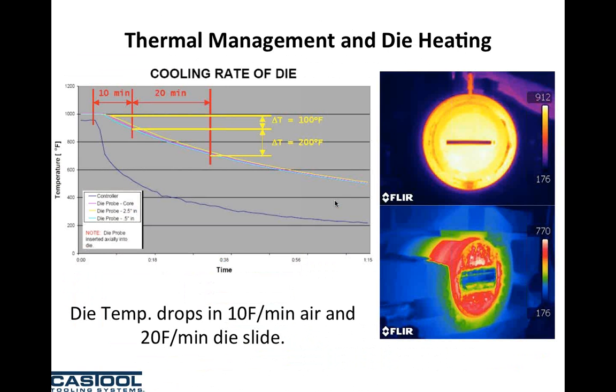As a rule of thumb for 6063 alloys, we say 10 degrees Fahrenheit relates to about 1% rate of flow. So for every 10 degrees colder your die is than billet temperature, it requires 1% more force, or the flow through the die is reduced by 1%. So if the die was 100 degrees colder than your billet, 860 billet and 760 die, it would take 10% more effort to extrude the die.